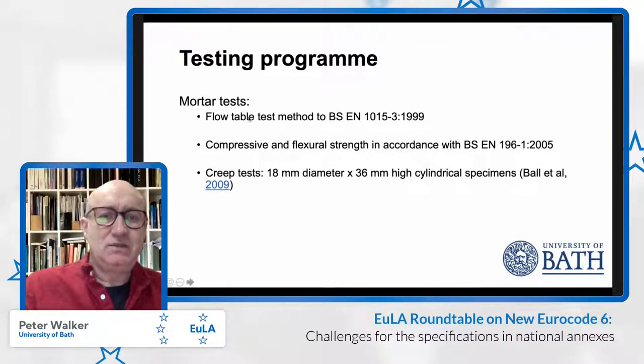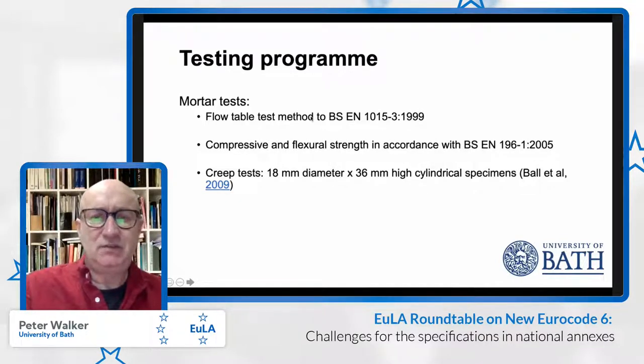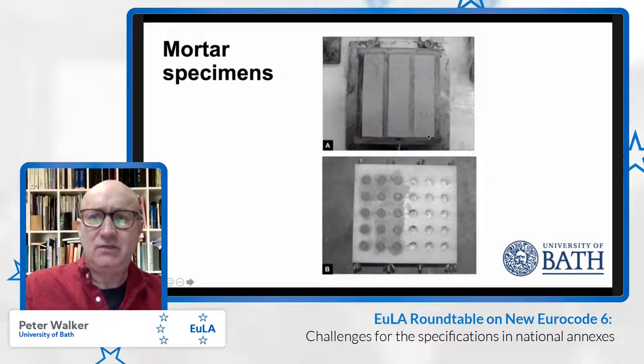So the testing of the mortars, as I said, we did flow table tests, and we did these regularly. We did compressive and flexural strength testing, and we also did creep testing. So the first two tests are set by Euro norm standard procedures, and the last test, the creep test on the mortar, was following a procedure on hydraulic lime mortars, which were on small cylindrical specimens 18 millimeters diameter and 36 millimeters high. So here are just the casting of the specimens, a plan view of the standard specimens for flexural and compressive strength in accordance with the Euro norm. And then here casting the small cylindrical specimens for the creep testing.